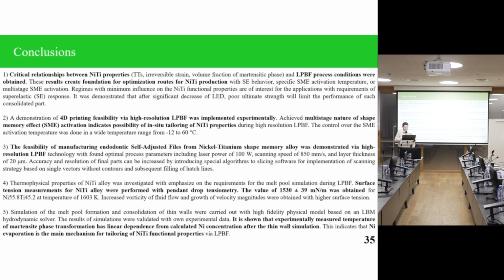Then self-adjusted files were manufactured by high-resolution laser powder bed fusion, and enough resolution was achieved for this instrument. Then some thermophysical properties were investigated with emphasis on the simulation of the melt pool. So surface tension value was received. And finally, by summarizing the experimental and simulation results, it was demonstrated that the main mechanism for tailoring of functional properties, or shift of transformation temperatures, is related to the different evaporation dynamics for nickel and titanium components.